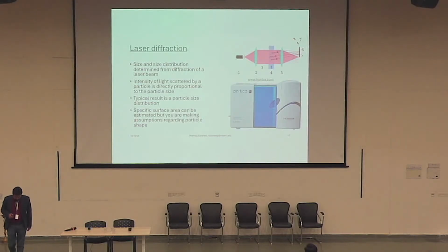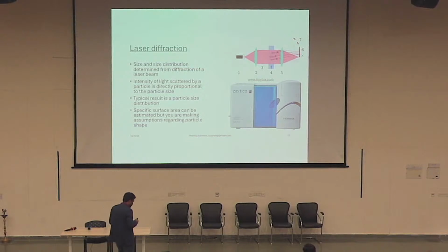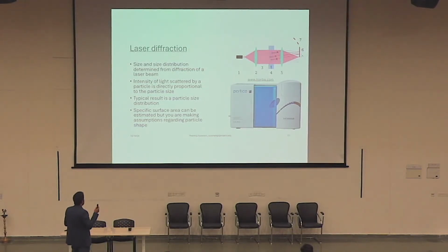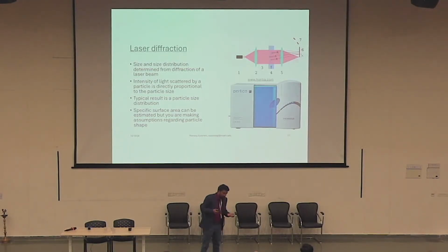Laser diffraction. So laser diffraction is basically a technique in which you hit particles with a laser, and then that laser diffracts. And depending on the size of the particle, the intensity of light scattered, the angles of scattering, etc., change. So you get a particle size distribution as a result from this measurement. So to a certain extent, it's similar to the electron microscopy. However, in the electron microscopy, you have to do a lot of analysis to get that distribution. Here, you get that distribution based on the scattering behavior.